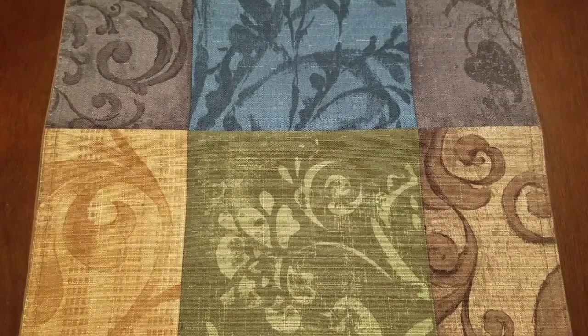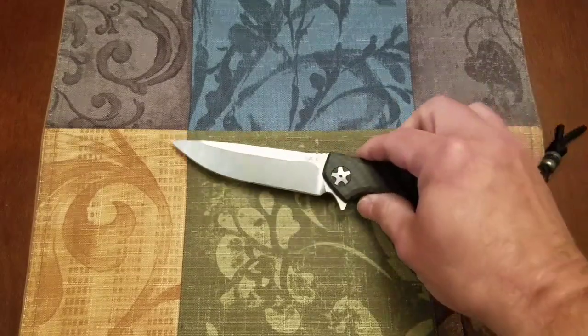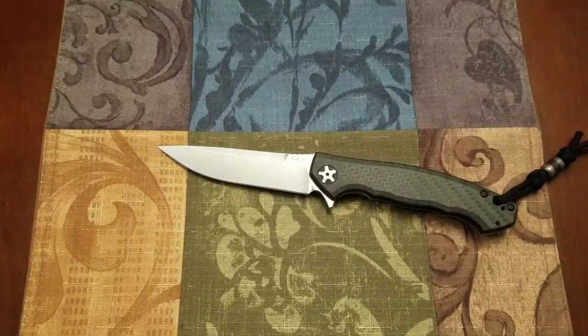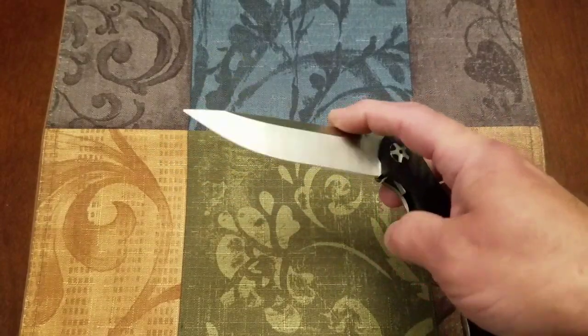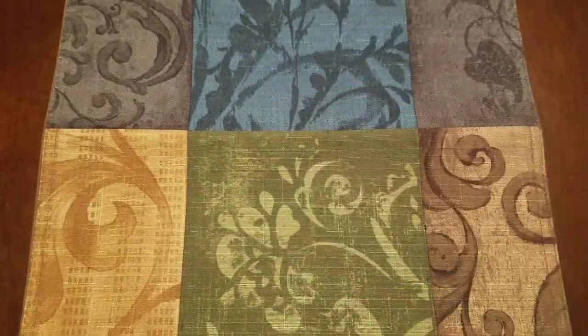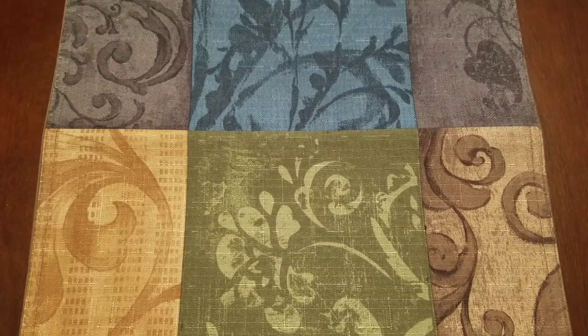Now, the next thing we have in the high ends is S35VN, which is an evolutionary version of S30V. They added niobium to this and a few different changes, and what you got was the increase in the carbides. You got increase in toughness. Now, initially it was said it was going to be more wear resistant, but across the market with different manufacturers, you've seen that S30V, the original version, was a little more wear resistant.